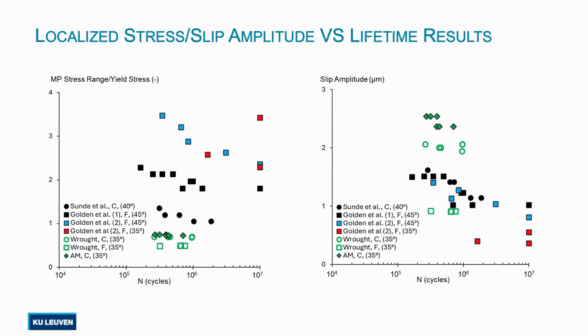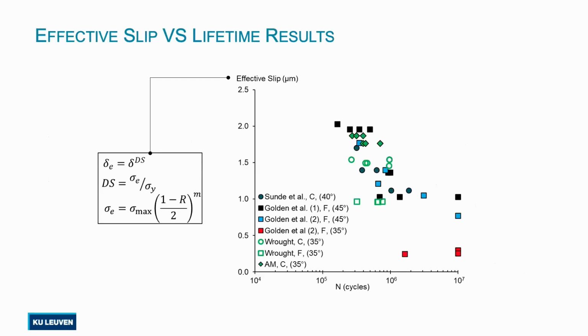So then we have here the maximum principal stress distribution range, and then we have here the slip amplitude. But again, we see that the slip amplitude is also a very important factor at the contact interface. Then we define the effective slip amplitude, which gives us an overview of the stress distribution at the contact interface, plus the slip amplitude, which are very important in this case.